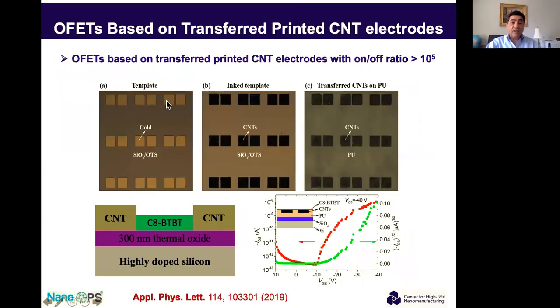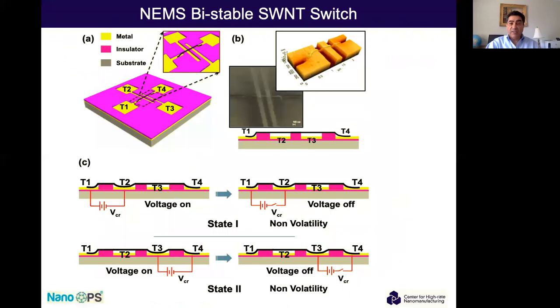This particular one is using the first technique that we use, where you use a template and you transfer. And this is using carbon nanotubes as the electrodes here. So this is the template. This is the template after inked with carbon nanotubes. And this is the printed carbon nanotube source and drain on polyurethane, as you can see here. I included all the references here, so if you would like to look at some more.